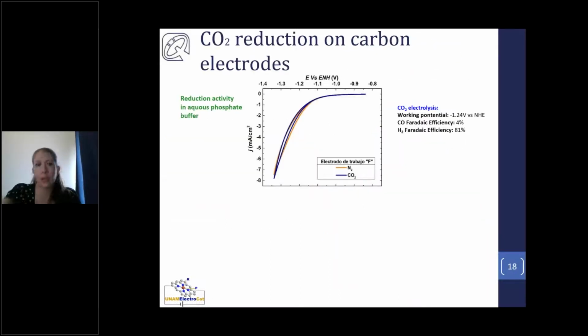That's why we were surprised when we started measuring blanks. What we measure as blanks are our carbon electrodes, and in this case we were using carbon paper. For our blanks, we perform the same cyclic voltammetry that we carried out for our catalyst, in the presence of nitrogen and CO2. When we do this in aqueous electrolyte, we see that the current in the presence of CO2 is basically the same as in the presence of nitrogen. So we assumed that all the carbon electrodes were doing was reducing protons to form hydrogen. However, when we look at the electrolysis, we actually see that some CO2 is being reduced to CO.